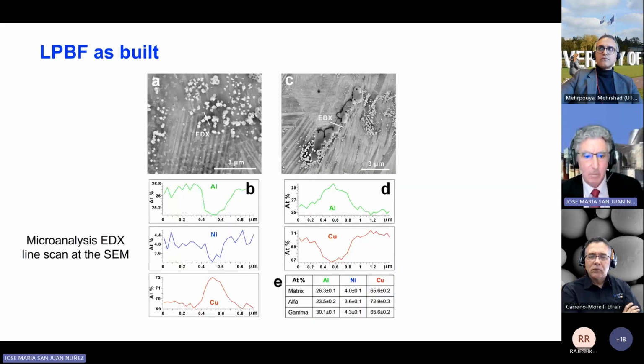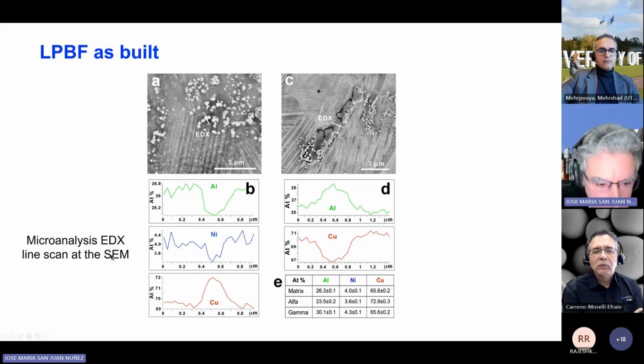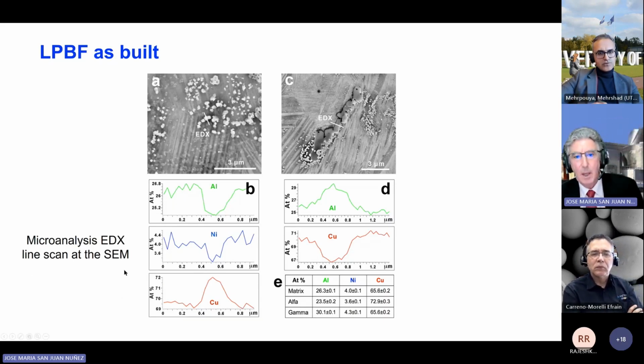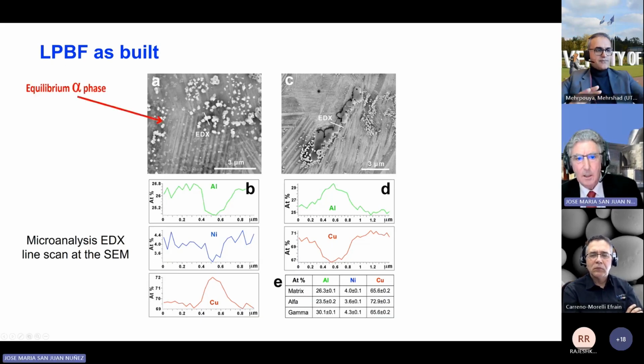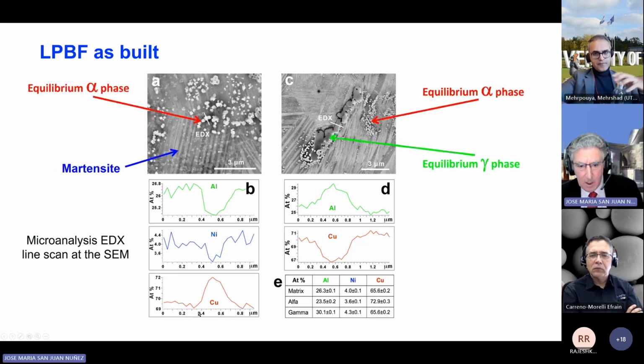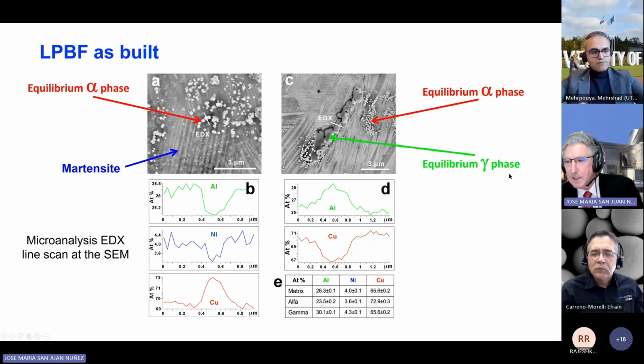This is seen in our images of the scanning electron microscope, and we have done microanalysis, EDX, and line scan at the SEM, and these are the kind of precipitation you can find just after building the laser powder bed fusion sample. So in this case, these precipitates are copper-rich and poor in aluminum and correspond to the equilibrium alpha phase, this one or also this one. And on the contrary, this other equilibrium phase that I can put in green corresponds to a phase rich in aluminum and poor in copper. So this is the equilibrium gamma phase.